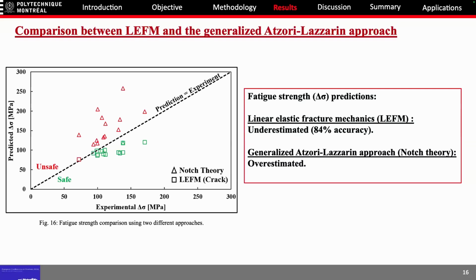And the LEFM, represented by squares, is mostly green because it's a safe approach when using this graph, with a prediction accuracy of 84%. So basically, LEFM is a safe approach for this kind of volumetric defect that we can find in these welded joints. But why are LEFM predictions more accurate than the notch theory?